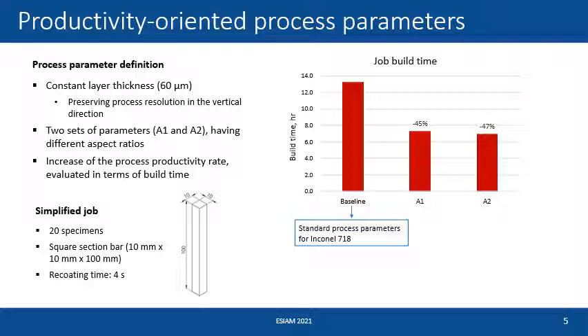Were selected two sets of parameters, named A1 and A2, having different aspect ratios of the melt pool. These process parameters were compared in terms of productivity rate by evaluating the build time in the production of a simplified job formed by 20 specimens. Each specimen is a square section bar, 10 millimeters by 10 millimeters by 100 millimeters, and considering a recoating time of 4 seconds between each layer.